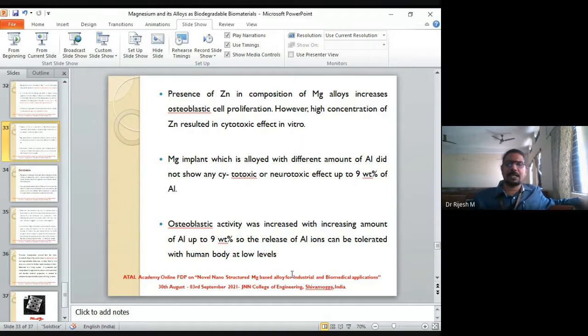Osteoblastic activity increased with increasing amounts of aluminum up to 9%. So the release of aluminum ions can be tolerated by the human body at lower levels. But the problem happens when it goes to a higher level.